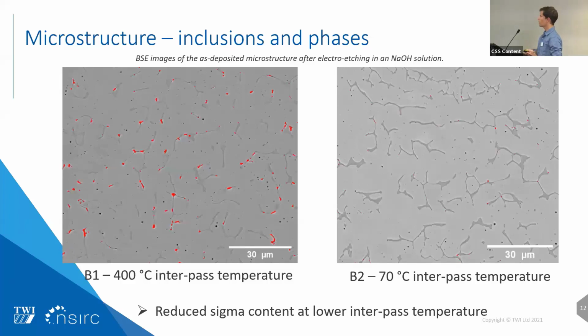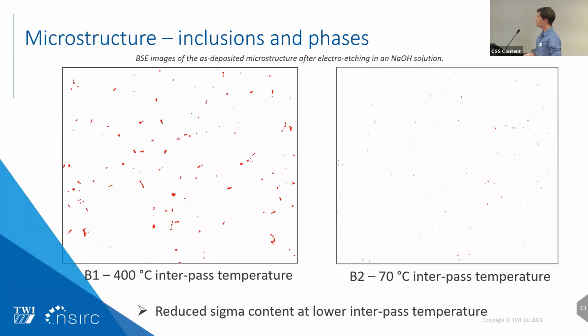Here I've highlighted the sigma phase that has been revealed using the same etching as before. We can see that we have indeed less sigma phase in wall B2 than in wall B1. By subtracting the background, we can still see that we have some sigma phase present in wall B2, except those phases are way smaller than in the first wall, wall B1, at higher interpass temperature. So playing on the interpass temperature can successfully affect the sigma content you end up with in your build.